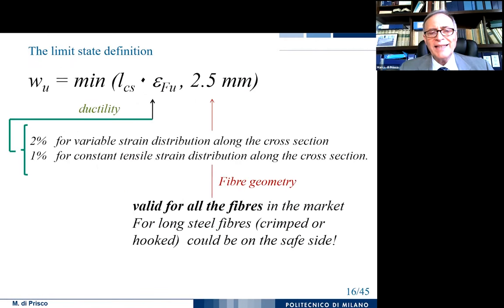We also have to define an ultimate crack opening, and usually the ultimate crack opening takes into account the minimum between two main requests. One is a request in terms of ductility. So we start from the definition of a final strain of 2% for variable strain distribution along the cross-section and 1% for a constant strain distribution along the cross-section. And this is a requirement due to ductility.